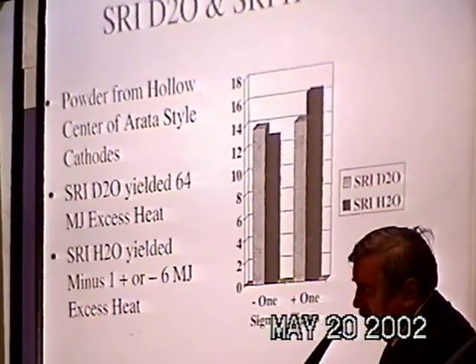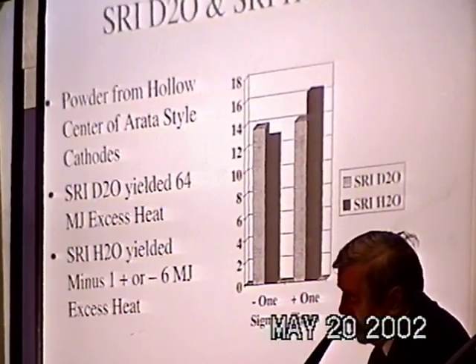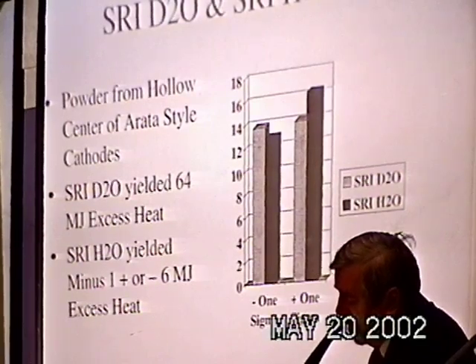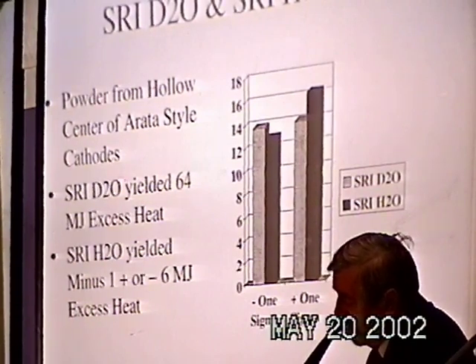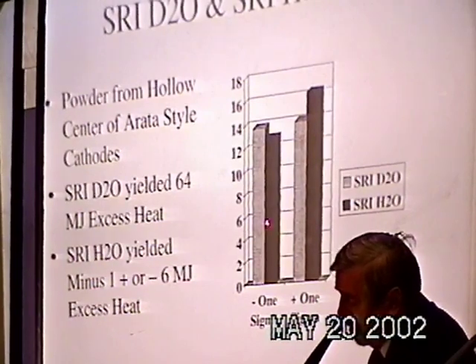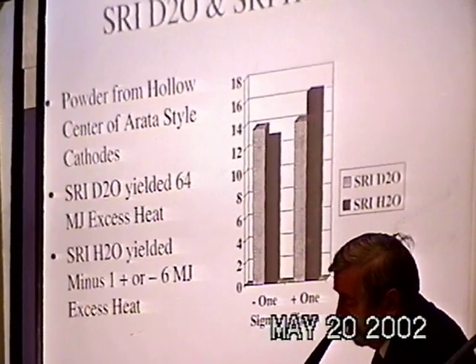Then SRI attempted and did some supporting replicas of the Arata style of cathode and observed excess heat to the tune of 64 megajoules in the D2O case and -1 plus or minus 6 megajoules in the hydrogen or water case. And here are the 2 cases where I had 2 sets of these. You can see that they're not very impressive, but it is still positive relative to the terrestrial value. 12.5 is the terrestrial value. So the D2O is slightly higher than the H2 in this case. In this case, it's reversed, so it's a little ambiguous, but the limits of error are rather high for this H2O case, with a lot less lithium present. So the limits of error include this difference.